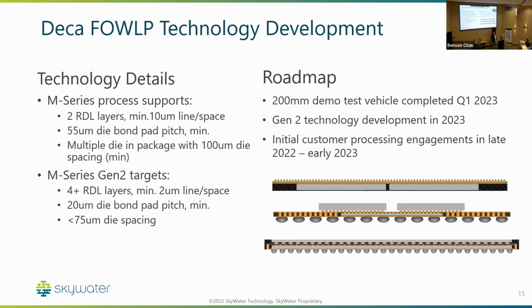The Gen 2 targets will push that number of RDL layers to 4. It'll also push the dimensions down to 2 microns. So again, a tremendous increase in the amount of interconnectivity that's possible in the package. 20 micron die bond pad pitch now instead of 55. So you're looking at a much higher interconnect density on the devices themselves and a reduction in the die spacing. So we're cutting down the interconnect length between the devices as well.